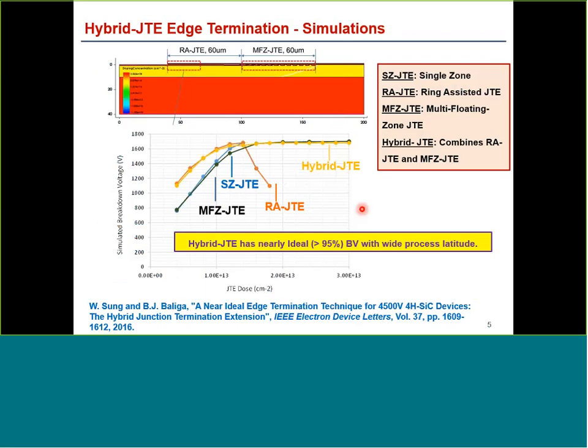Before we could make any devices, power devices, we needed to make sure we had a good, robust, high voltage edge termination. So we did an extensive study of various techniques to create the edge termination. This included the single zone JTE, the ring assisted JTE, the multiple floating zone JTE, the hybrid JTE. And you can see from this chart that among all of these, the hybrid JTE, the orange line, has the broadest spread, meaning it has a lot of wide process latitude and it's easier to fabricate. And it also gives nearly ideal breakdown voltage.